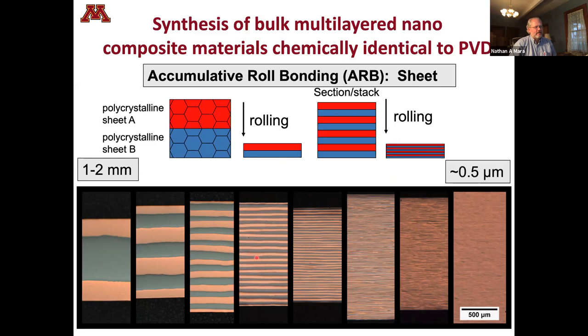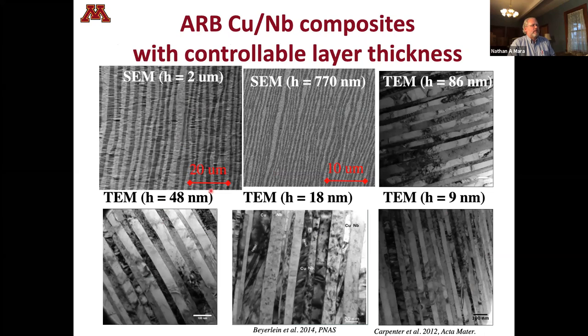You lower your layer thickness, but you keep your overall sample thickness pretty close to the same. As you repeat this, the layer thickness gets smaller and smaller, and you can reduce it all the way down to sub 10 nanometers. When you think about how big an atom is, about 2.5 angstroms, so 0.25 nanometers, we're talking about just a few atomic diameters across each one of these individual layers. And so it becomes a very, very thin layered material.